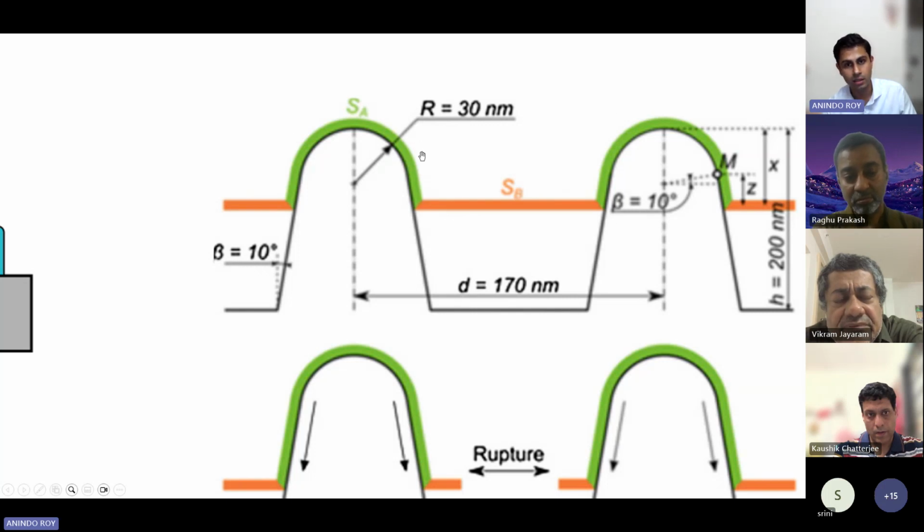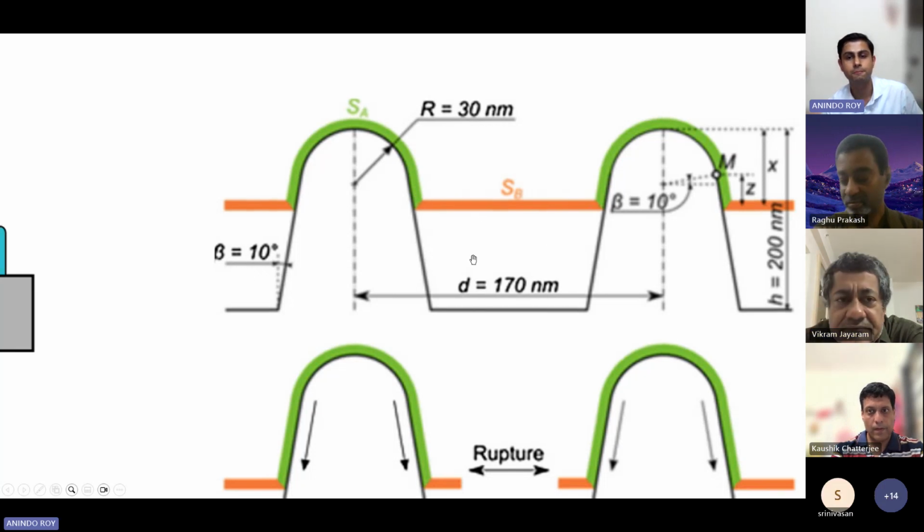So basically, as the adsorption progresses, more and more points, as they get adsorbed, essentially become immobile. They are fixed on the pillar point there. So now only the region that is suspended takes the strain. Strain doesn't build up on the curved surfaces. There will be a certain small amount of strain on the curved surface as well, but mostly on the suspended region.